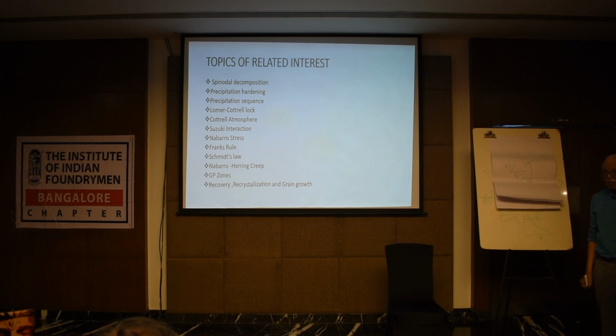Serrations are also very interesting. Once again, due to the Cottrell atmosphere, what happens is it gets locked from the core by carbon atoms, then the carbon atoms diffuse out, the dislocation can glide, and then once again carbon atoms diffuse back inside the core and lock it up. That's how you get the serrations on the stress-strain curve. Okay, next one.